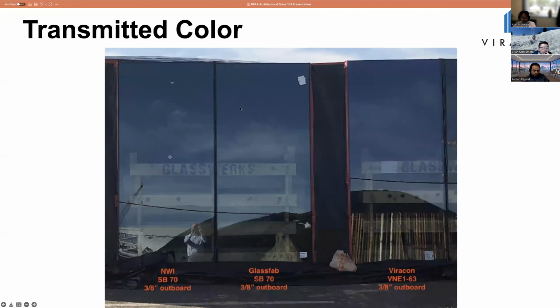So we had another project in Southern California where Solar 70 was specified, and they supplied mock-ups for the project. And they had picked Solar 70 because in the samples, they thought that the Solar 70 was just a little more neutral in transmitted color than Viracon's. If you look at this photograph and you look at two different regional fabricators doing the Solar 70 and then Viracon, the one on the right, I think you can see that if you look at the color of the wood, Viracon's is actually just a little more neutral than the Solar 70 in transmitted color.